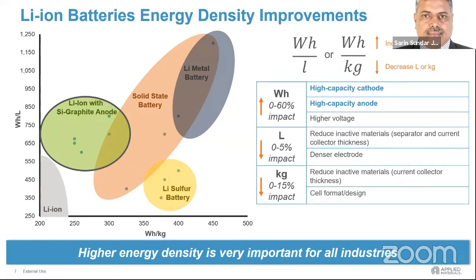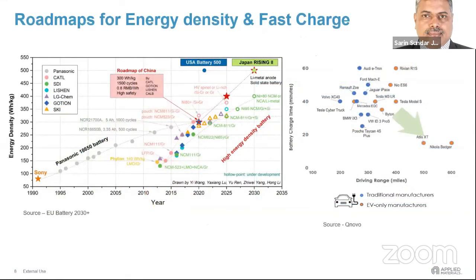Where we are today with respect to the roadmap, I want to quickly share a few things here. There are a couple of slides. One is taken from the EU Battery 2030 Plus. Today we are around 300 watt-hour per kg with various high volume manufacturing companies. And especially today, on March 3rd, 2021, we could see the news that a company in China is releasing a lithium iron phosphate battery with 480 kilometer range. So even lithium iron phosphate is now competing with NMC at 170 watt-hour per kg. And one of our customers is also promising to give 210 watt-hour per kg with lithium iron phosphate.